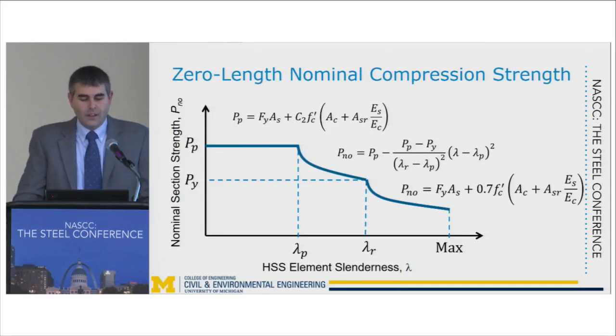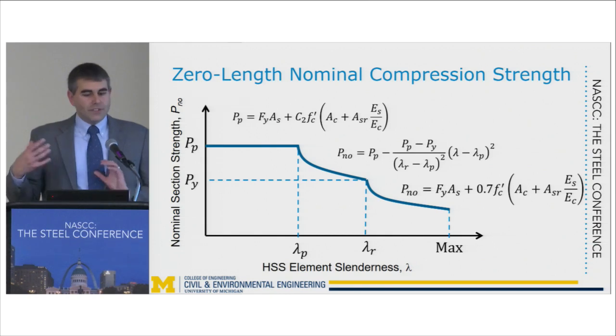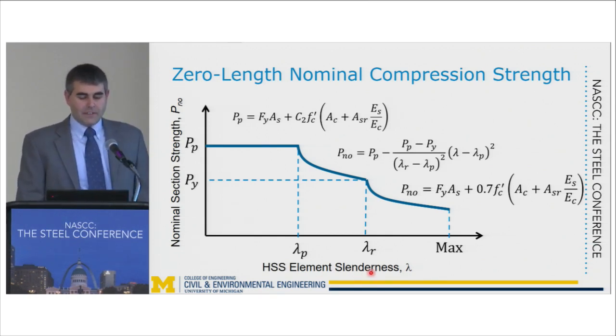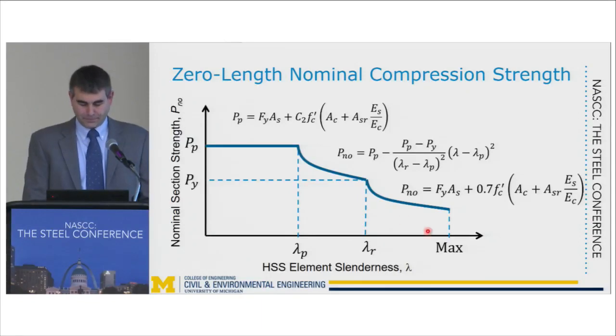And in this case, the concrete undergoes inelasticity and even more significant volumetric dilation, which causes more stress on the HSS walls. So if we take all those zero length nominal compression strengths and plot them with respect to the element slenderness, you end up with a plot that looks like this. So you can see this plot's slightly different than what we see for just a bare steel member, where you'd have a linear stress distribution here. Instead, you have the quadratic stress distribution to account for essentially the confinement that you get from the hollow structural section.